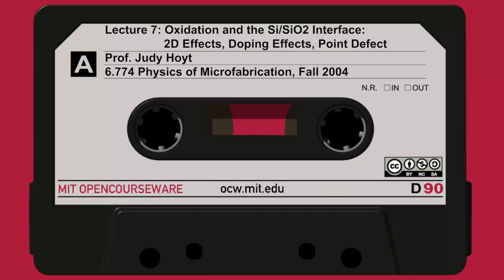So this is the model run without stress, and people did these models. And they found, oh, it doesn't really agree with what we get experimentally when we grow LOCOS. We do a cross-section and we look at it. That's not what it looks like. In fact, what they found, it looks more like what's on the right. And what's on the right is the SUPREM 4 model, but this time turning on the stress dependence.